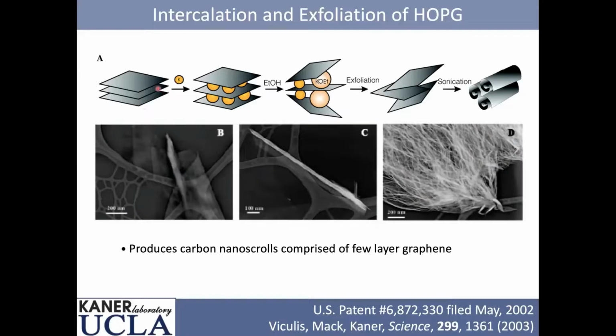So we heated graphite with potassium. There's a well-known reaction. It makes something called KC8. And between every layer of carbon goes potassium plus. And this material is quite reactive. So you can take water or alcohol, and if you expose it to it, it literally exfoliates. It blows apart the layers. So we did this with alcohol under controlled conditions, and then we just sonicated, and it scrolls.